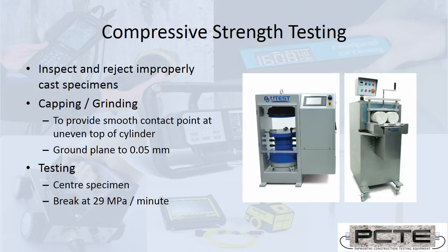As part of that, the top surface, which was levelled but not left entirely smooth, needs to be allowed to be flat, plain and square. So commonly sulfur capping or grinding will be used. Grinding's proved to be an easier system for this, grinding plane to 0.05 of a millimetre, and the crushers may better represent the strength depending upon, again, how those samples have come together. Standard also defines the rate.